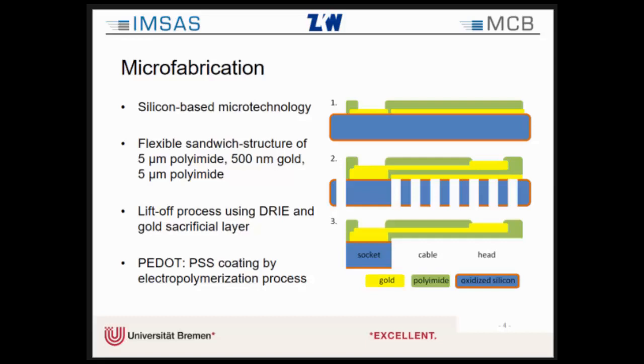And after that, we spin coat and structure the second polyimide layer to achieve the sandwich structure of 5 micrometer polyimide, 500 nanometer gold, and 5 micrometer polyimide. So in total, we have a thickness of about 10 micrometer. And to be able to release the array from the wafer in a safe way, we developed a lift-off process using a deep reactive ion etching of silicon and the etching of the sacrificial gold layer using iodine solution. Of course, for that step, we have to protect the gold of the electrodes and the soldering pads. After releasing the array from the wafer, we solder the Omnetics connector and we coat PEDOT-PSS using an electropolymerization process.